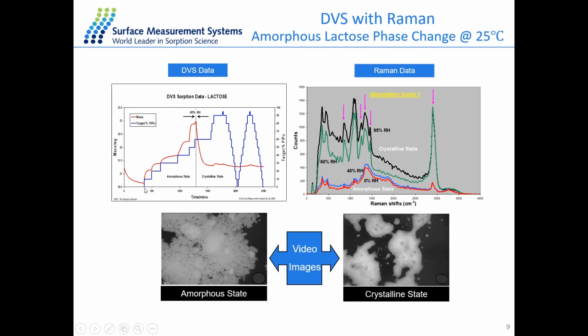The red line here is the change of mass for the sample. Below 60% RH, this amorphous lactose sample has a very good uptake. It reaches equilibrium and then jumps to the next stage. At 60% RH, you will notice a significant decrease in the mass of the sample, and that's because of the amorphous to crystalline phase change, because the crystalline material has smaller surface area as well as less sorption capacity. This kind of phase change is irreversible, so it doesn't happen in the second cycle. So that's just some observations from the DVS data.